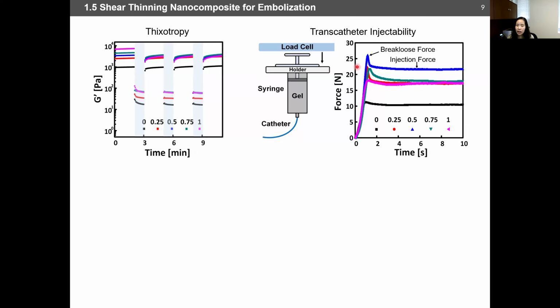And one important thing, I keep emphasizing, is that this is a transcatheter material. You may already see a lot of injectable materials, but those are really in short needles that can solidify depending on the interaction. Again, transcatheter, what we're talking about here is a 150 centimeter long catheter that can go down to 1.8 French, which is sub-millimeter in cross-sectional diameter.